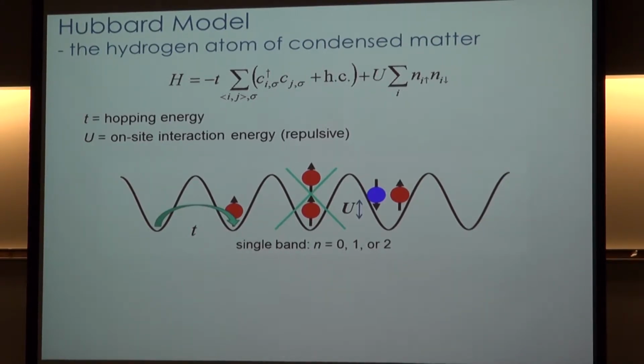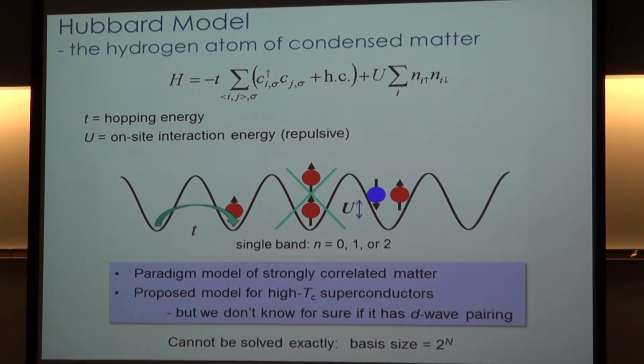Now, I'm considering just a single band Hubbard model. So here, in order to satisfy the Pauli principle, we can only have 1 particle per spin state per band. And so we're going to ignore higher band effects. That means we have to be sufficiently cold that none of the higher bands are excited. All right, so in actuality, that's the entire model. Now, it seems simple enough, and it is actually easy to write that down. It's a paradigm model of strongly correlated matter because it turns out that this model can't be solved in all generalities. So for arbitrary density and arbitrary interaction strength, we don't know exactly what the solutions of this model are.